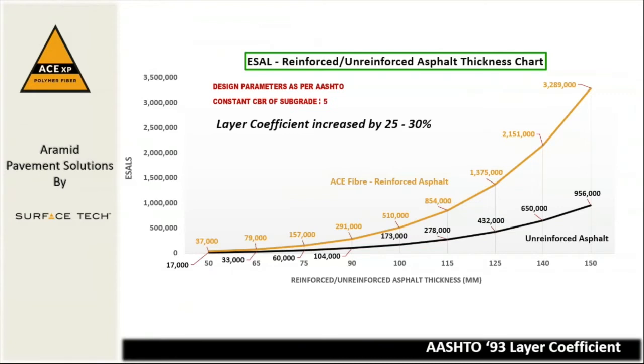Another way to quantify the improved performance is to look at the effect as a design variable. Back calculation from our field testing has shown that the layer coefficient used in an AASHTO 93 design can be increased by between 25 and 30%. If you are currently using a value of 0.42 for your asphalt coefficient, the addition of ACE-XP would allow you to use 0.53 for the design.